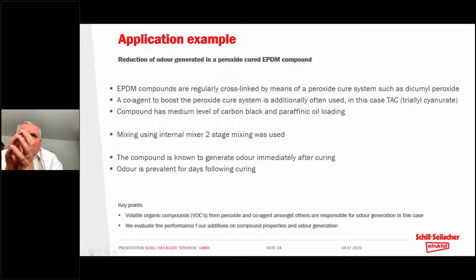And here quite often you'd also find a co-agent used to boost the peroxide cure system. In this case, the example that I'll show you shortly, we have TAC, triallyl cyanurate, as a kicker, a co-agent, if you like, to accelerate or to maximize the cure efficiency. And then a medium level of carbon black and oil loading. This compound is known to generate odor immediately after curing, and a certain level of odor is noticeable for several days following curing in the vulcanizate.